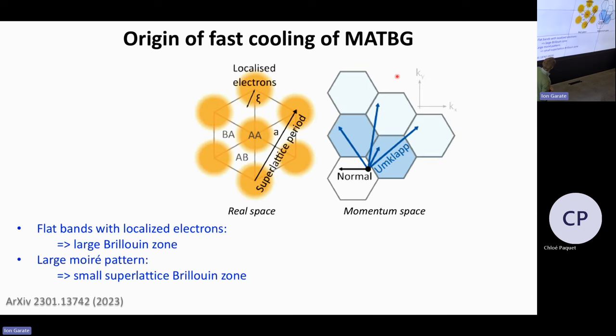And now we get to the explanation. So what's going on is that you actually have very low energy phonons from the Moiré pattern. So this gives rise to new phonon bands with very low energy. So of course you don't just have the normal graphene with its typical phonons, but you have additional phonons from the Moiré pattern. And these are very low energy that you can couple to. And now the question is, how do you couple to these phonons? Because your Dirac cone or your parabolic band, they have really, you know, very high dispersion. These very low energy phonons will have super flat dispersion. So it's not so easy to couple between those.